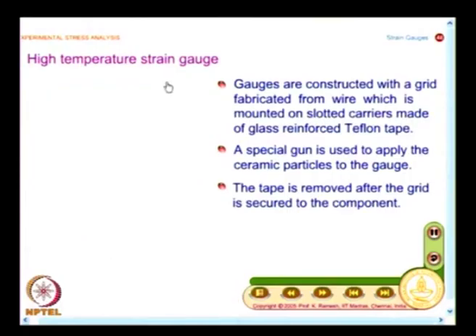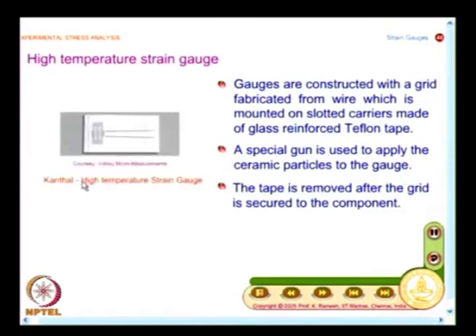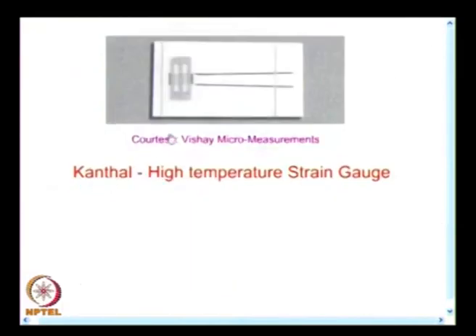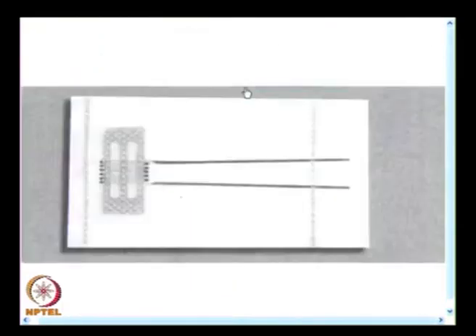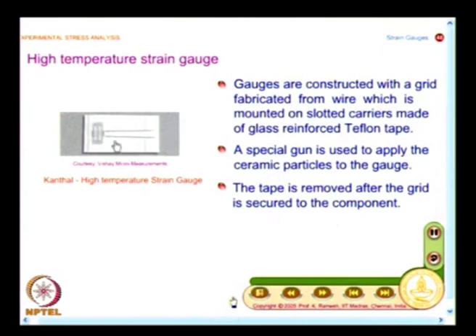And this is given by Vishay Micro Measurements, and they have what is known as Kanthal, which is meant for high temperature strain gauge, and you could see the slotted Teflon tape carrier, and you have the strain gauge available like this. So, this can be used to put the ceramic cement and remove the carrier and put another layer. So, essentially you will have only a ceramic base and you will have a metallic foil. There is nothing like a polymer that comes in between. So, at such high temperatures they will not withstand that, they will disintegrate. So, in order to make sure that your instrumentation is good at that high temperature, you form a ceramic layer.